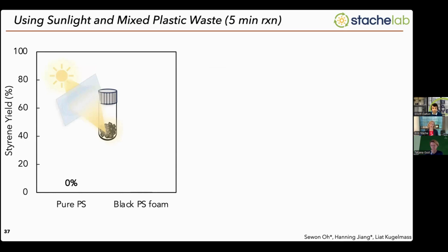It was completely intact. The solar radiation was not enough to depolymerize or photodegrade the material in the time frame that we looked at. However, when she took black polystyrene foam, so the sample that I had shown you on the previous slide, cut it up into small pieces, put it out and irradiated it with sunlight, what she found is 80% monomer generation. And this was in 5 minutes. So just 5 minutes of solar radiation, she could depolymerize the black polystyrene into 80% monomer. The mass balance was a small amount of dimer and trimer, as would be expected, but this type of styrene monomer yield is competitive with or outcompetes existing pyrolysis technology. And again, this is just using the additive that the plastics manufacturers are already putting in the samples.